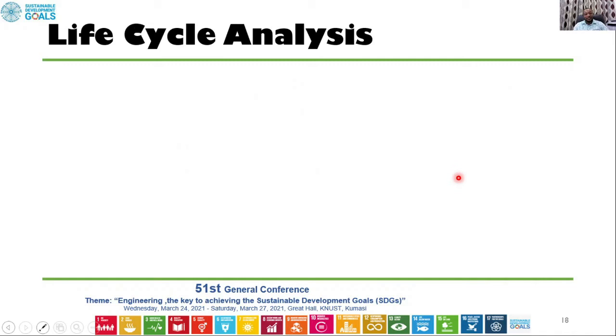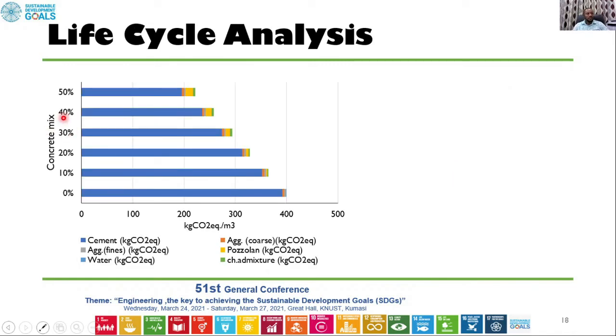So let's look at the life cycle analysis. The graph is plotted between concrete mix and the kilogram carbon equivalent per meter cube. So these are the key points you have to note from this graph. Number 1, the highest emission was the OPC concrete. So this is the OPC concrete. It means that it doesn't contain any Pozzolan. That was very high, around 400 kilogram carbon equivalent per meter cube.